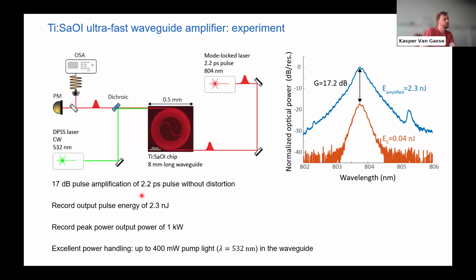And using this system, we really managed to get a pulse energy of 2.3 nanojoules out of our chip. And that's really about 20 times the previous record. So this is really unmatched in terms of pulse energy. And I think this is still the standing record for pulse amplification on chip. We could get peak output powers of 1 kilowatt.